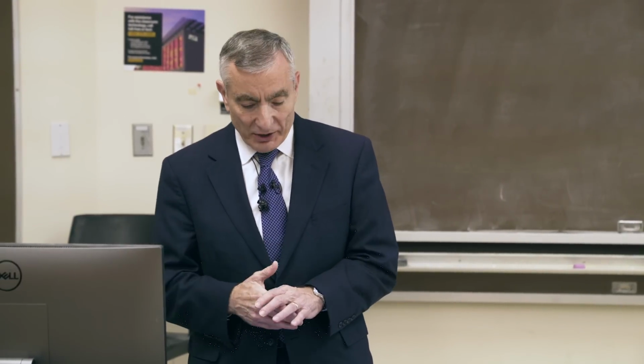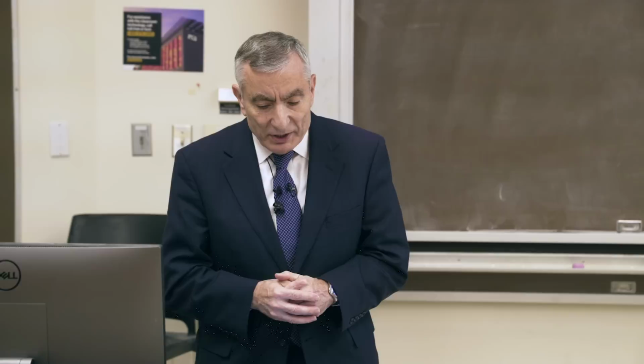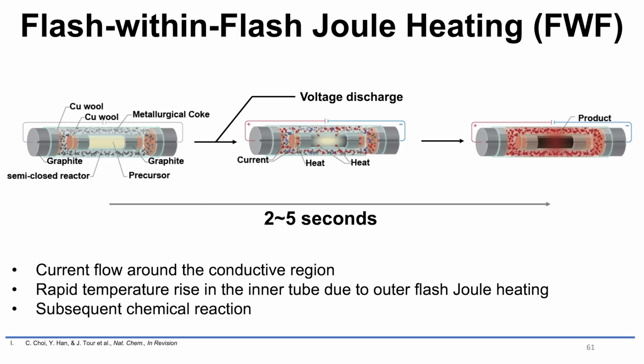conductivity to flash this. But say you don't want carbon around, because if you have metals with carbon, you often get the carbides, and we published a whole paper on metal carbides. Well, what we decided to do is if you didn't want to have carbon around, you put your inorganic components in an inner tube, cap it, and then put an outer tube around it. You put this outer tube around it and you flash the outer tube, so there's no carbon on the inner tube. You flash it, you have to run it like 2 to 5 seconds. You have to run it longer because now you have to have heat transfer into the inner tube, and you make your materials in here that have never seen carbon.